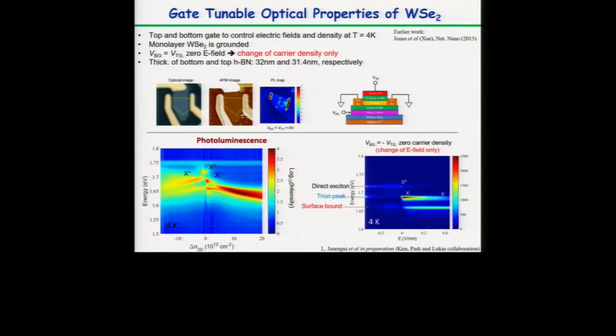And they get reduced energy because of this screening effect, because we're adding more and more of these electrons or holes. However, when we do electric field dependence, because this is a truly 2-dimensional material, there is no dipole moment to change energy. So we don't see, at least, a Stark shift effect. We don't see a change in energy. But we still see this direct exciton, the trion. Unfortunately for tungsten diselenide, there are these surface-bound peaks, which are usually related to disorder in the sample.